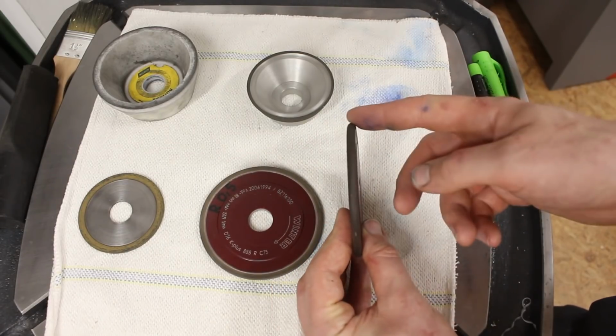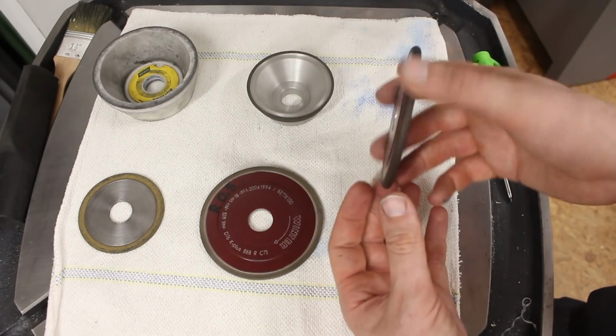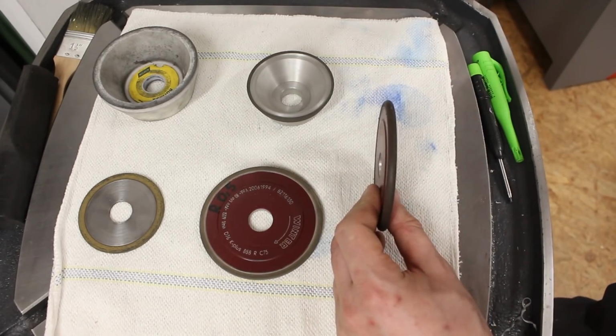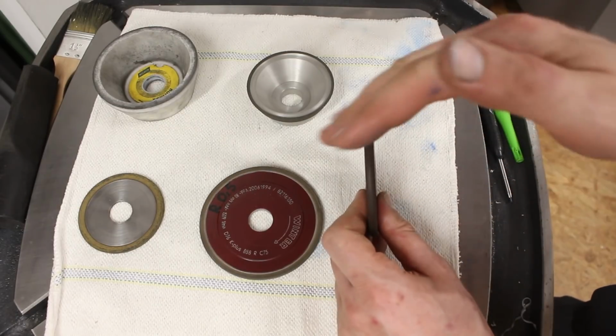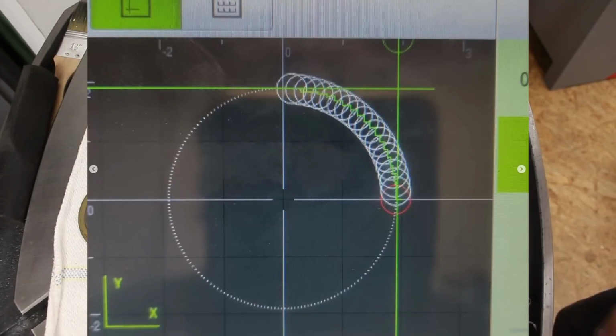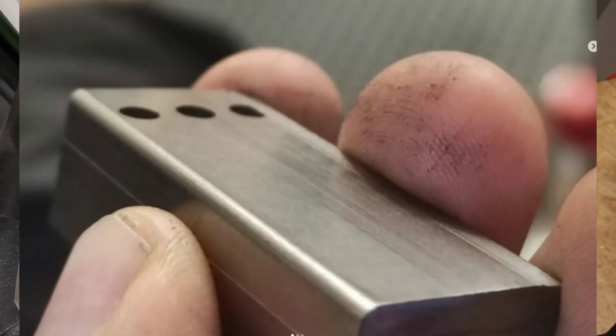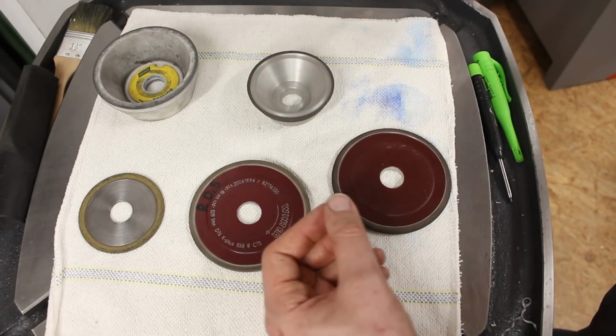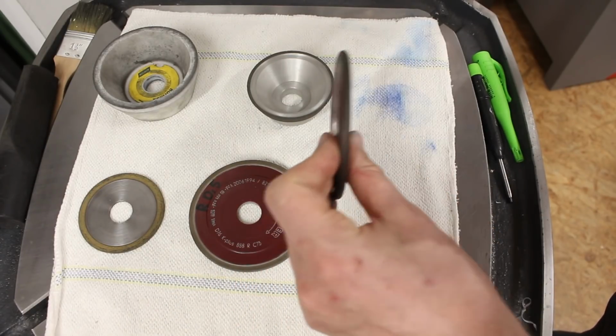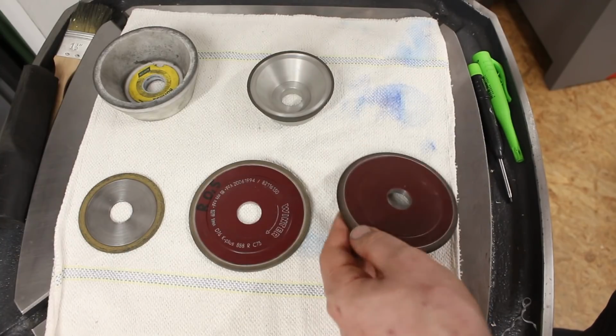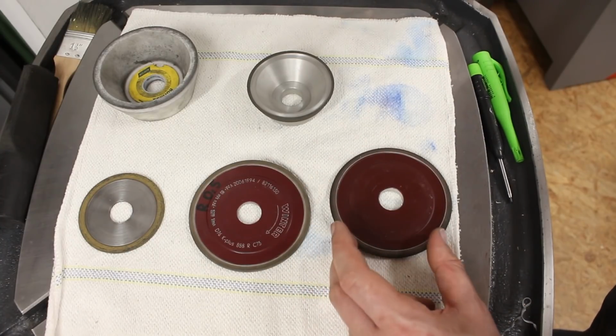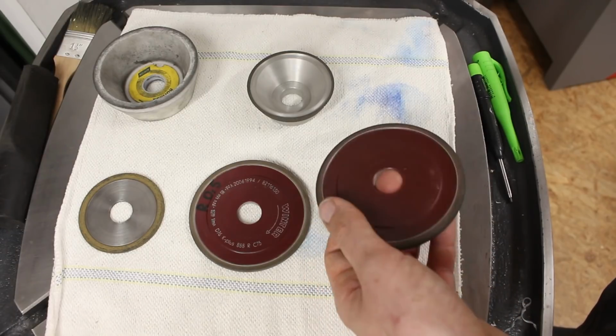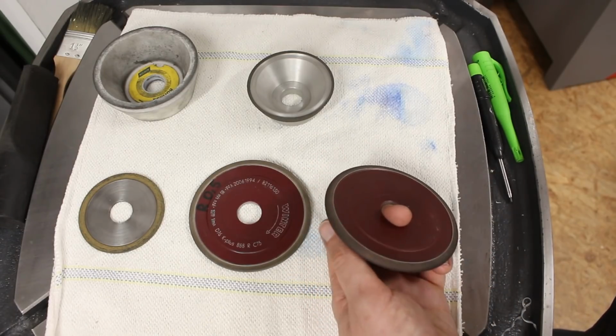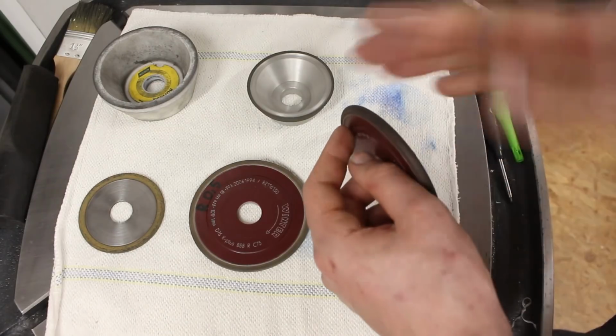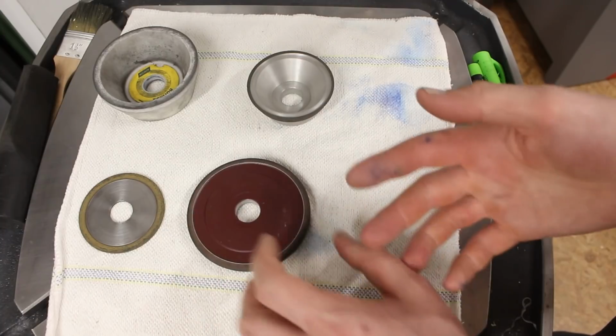You can not only form this full radius, grinding a concave slot or a concave corner, but using math and figuring out your tool path, and especially if you have a DRO, you can use a formed radius wheel or a wheel like this, like you would a bullnose or a ball end mill on a CNC mill, and step off a profile and grind a profile that way. I learned this technique from Adam the machinist, and it's a very powerful technique if you want to grind carbide but don't want to pay money for a specialized form wheel and don't have a CNC grinder.